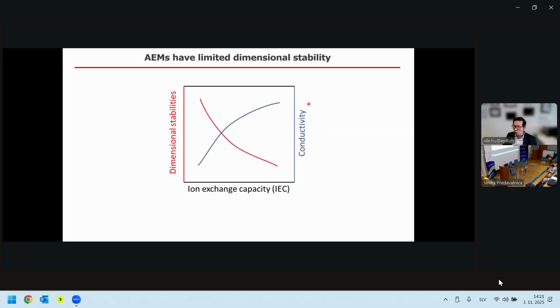A third challenge is to do with how you use it in devices, because in devices we actually need mechanical stability. Now, typically we often call it also dimensional stability. The problem with dimensional stability is that when we need high conductive AEM, we typically need to have really high ion, okay, functional group. So the ion exchange capacity is high, you have high conductivity, but then you become really hydrophilic. You absorb a lot of water, and when you absorb a lot of water, you become a gel, and your mechanical stability just goes down, okay? And so that's a problem.